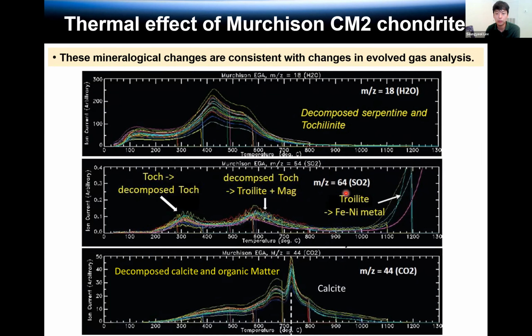And this data is showing the SO2 emission. So the first peak led to the decomposition of the tochilinite, and the second hump led to the decomposed tochilinite becoming troilite and magnetite. In the high temperature area, this troilite actually becomes the iron metal complex. So it's showing the loss of SO2 gas emissions.